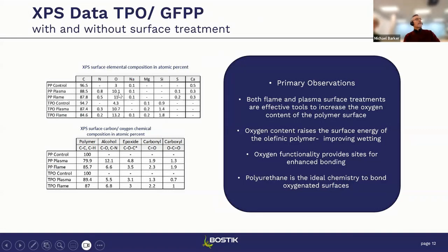And then if you drop down to the 3rd row for polypropylene with plasma treatment, that amount of oxygen jumps up to 10. And we also did the same with flame treatment. And so you can see adding that plasma or the flame treatment puts oxygen on the surface of the substrate. And then down below here, it basically can tell you what structural array those elements are in.